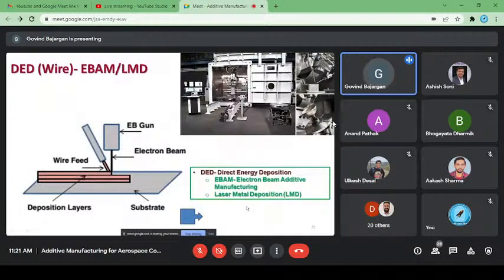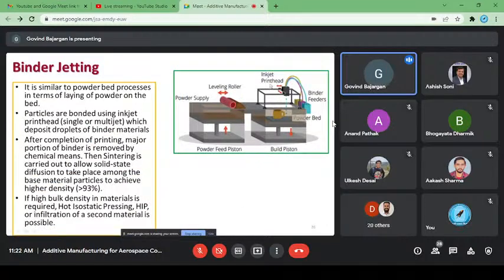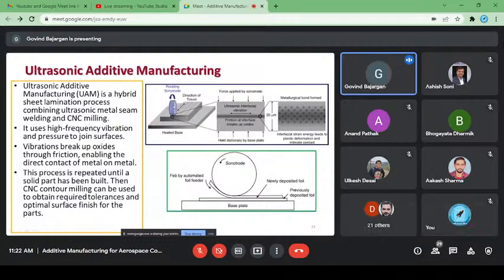So these are the various processes, and this is binder jet, where a powder bed is laid, and an inkjet print head sprinkles binder only at the locations as per the 2D drawing, and we build a 3D part. After completion of the printing, the part is removed. All powders are bound by liquid polymer, and subsequently it is subjected to binder removal and then sintering processes. In sheet lamination, a rotating sonotrode is passed as per the requirement, and we apply pressure as well as ultrasonic vibrations to make the sheets join at selective locations. So this way we can build parts. There are plenty of options available.